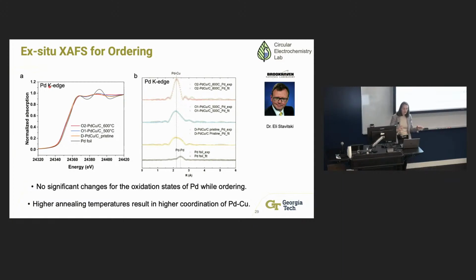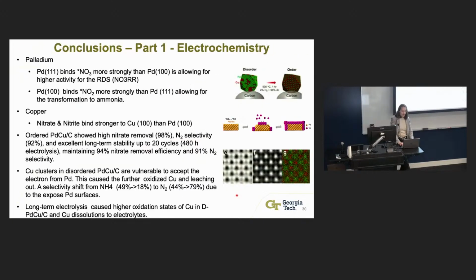We actually looked at the palladium and the copper, and this is the ex situ data. We also have in situ. I don't think I have it in this data, but essentially there was no significant change in the oxidation state, whether you had ordering or lack of ordering, but the higher annealing temperatures resulted in higher coordination of palladium and copper. Again, this can give us insights on how to design catalysts if we can discern what the critical electronic properties are. And with that, this is the end of my talk for today.